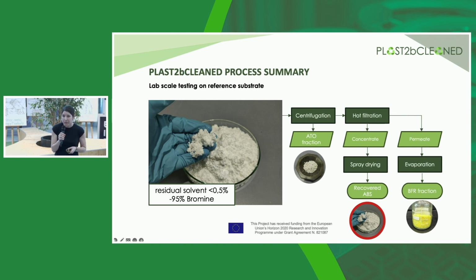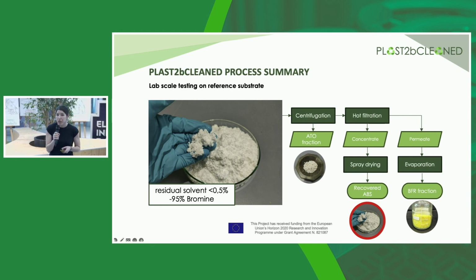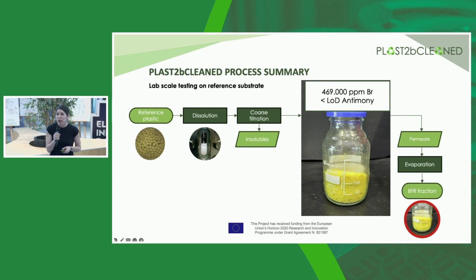For the polymer product, we also managed to have a very low bromine content. We achieved a bromine reduction of 95%, and residual solvent was below 0.5%. That was already mentioned by Sebastian. These numbers were even further improved down the process. And for the soluble brominated flame retardant, we recovered a stream with antimony content below the level of detection.